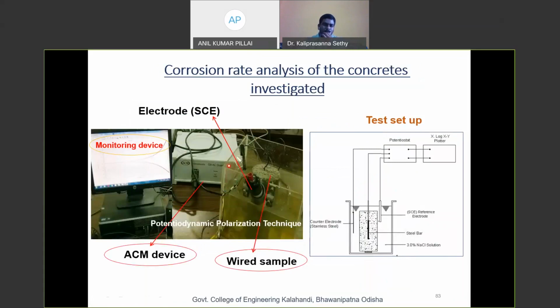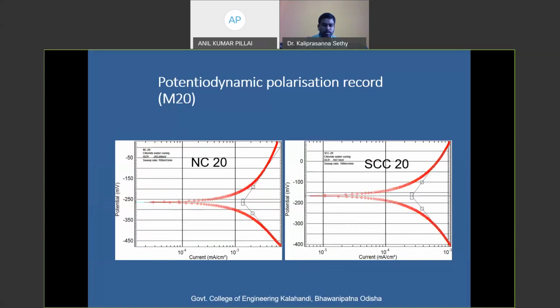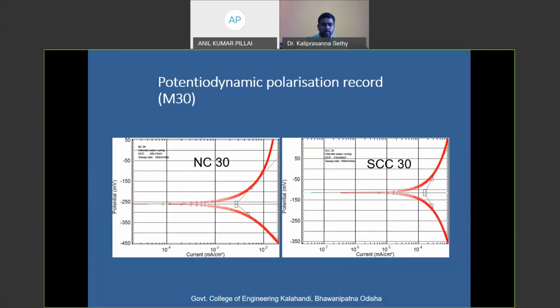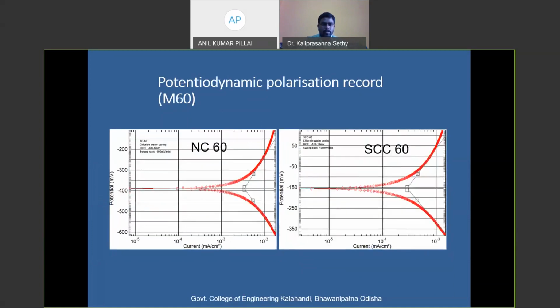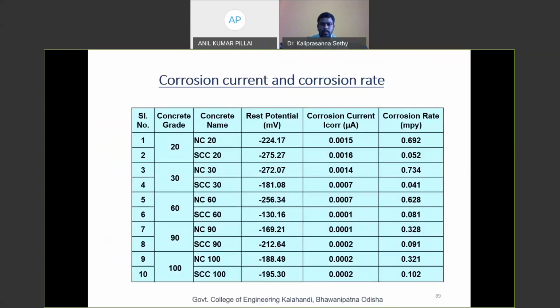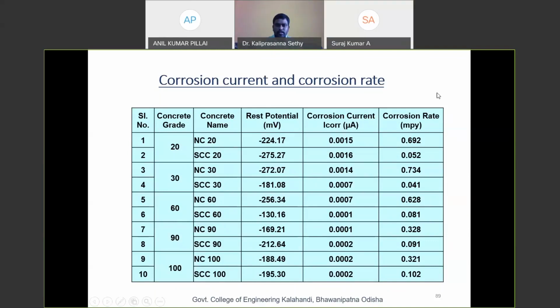Using this ACM device, which is a fully computerized device, we tested the corrosion analysis, and by the potentiodynamic polarization technique, we found these graphs between current and potential. These are the graphs observed from the digital analyzer of the ACM corrosion equipment, and this is all the data obtained from this digital equipment, the rest potential, that is potential and corrosion. From this we calculated the corrosion rate, that is the mils per year value.